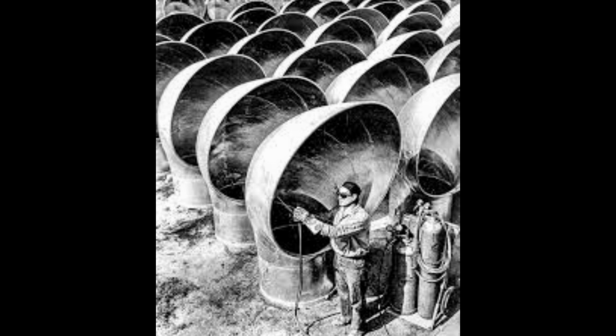The steel was the same. The welds were chemically identical, only the order of operations had changed. Yet the structural strength had improved dramatically, a result the engineers initially refused to accept. But now the physics behind the failures became unmistakably clear. Steel is not a static substance, it's a crystalline structure that reacts dynamically to heat and cold. When welders run a torch along a seam, they create a narrow zone exceeding 2,500 degrees Fahrenheit. The metal there expands intensely, but as it cools, it contracts. The surrounding cold steel resists that contraction, trapping immense tensile stress unless the welding order allows it to spread out.